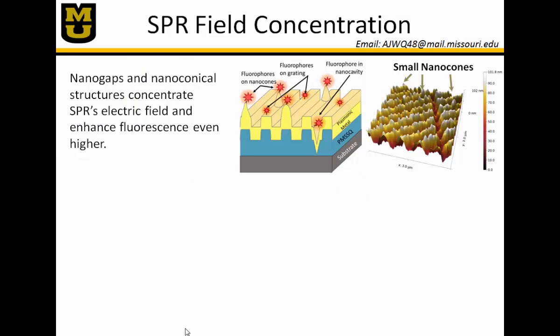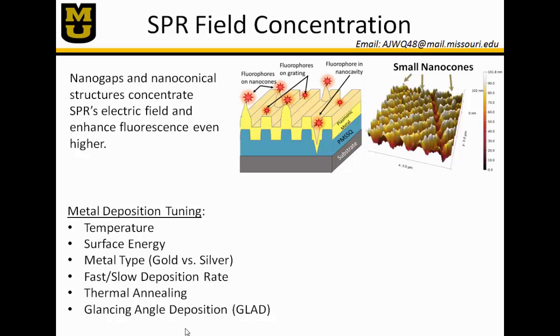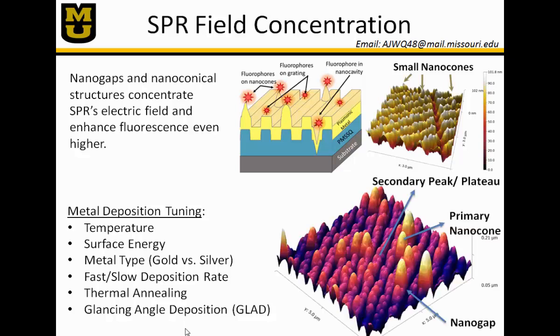So another way to concentrate those electric fields, you can incorporate nanoconical structures during metal deposition. So the way that we do that is by tuning your metal deposition, such as sample temperature, your surface energy, the metal type that you're depositing, through thermal annealing, and lastly, glancing angle deposition. So with glancing angle deposition, you deposit your metal layer at an angle relative to your grating, and what this forms are extremely large nanoconical structures as well as your grating. And these nanoconical structures behave as plasmonic antennas, and they can further concentrate this electric field and further enhance fluorescence.